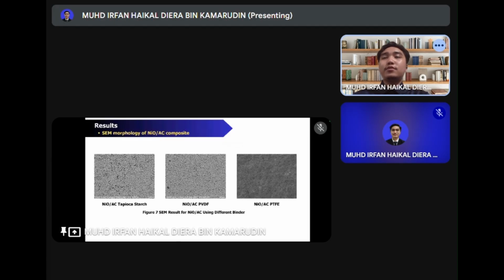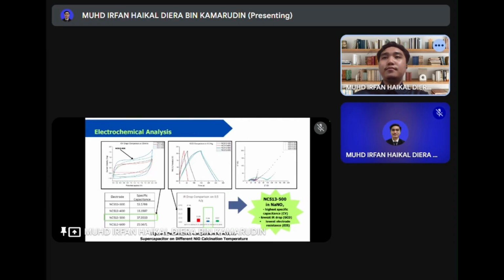Now, moving on to the result of our SEM morphology of NiO AC composite. On the left side, we see NiO AC Tapioca Starch. It has slight surface cracks due to the natural water-based nature. However, it still maintains good porosity and ion transport. In the middle one is NiO AC PVDF. It has a smooth and well-packed surface. This supports high electrochemical performance. And meanwhile, lastly is NiO AC PTFE. It has a compact and dense surface, which may hinder ion diffusion and limit performance.